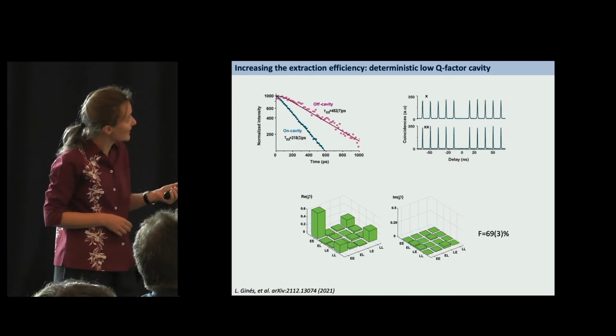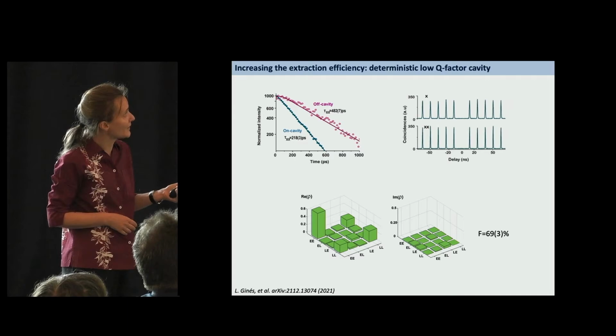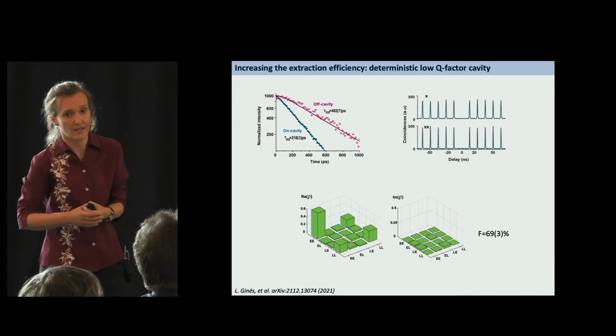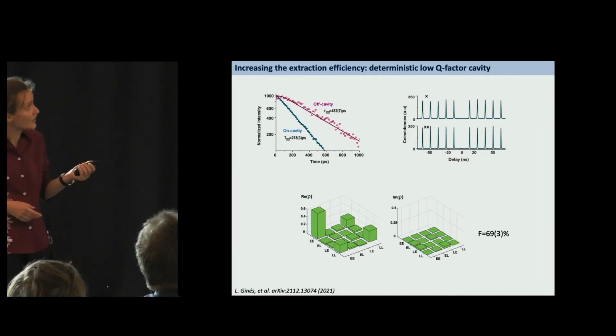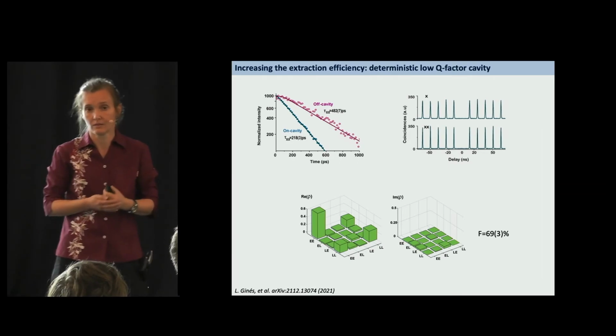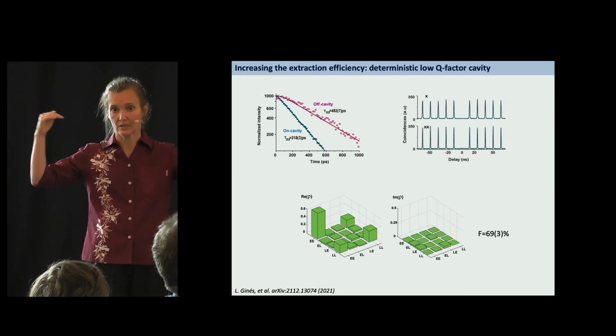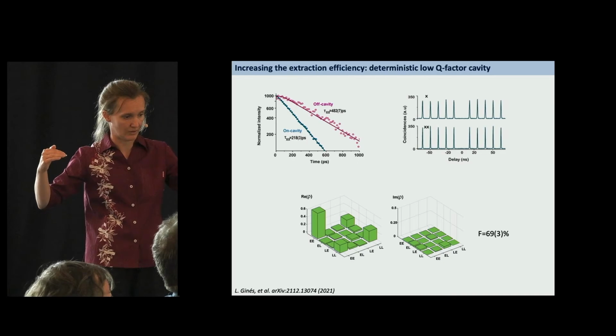And we also investigated if we do have any Purcell effects. So we're looking at many quantum dots that were resonant with the cavity and many that are not resonant with the cavity. And I have to tell you that this difference here exists not because we have a Purcell effect in the cavity, it exists there because the emission is suppressed at all the modes that are not resonant.